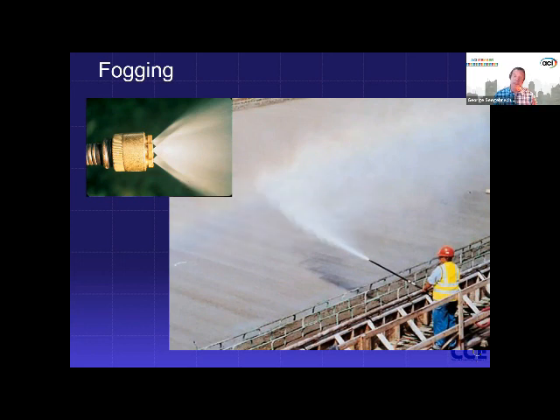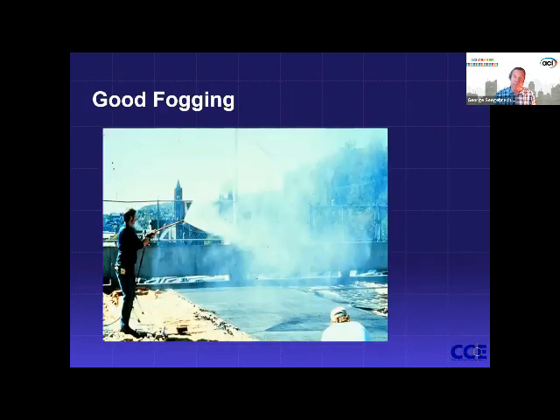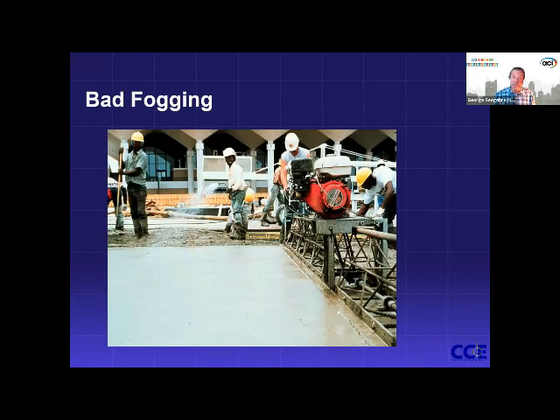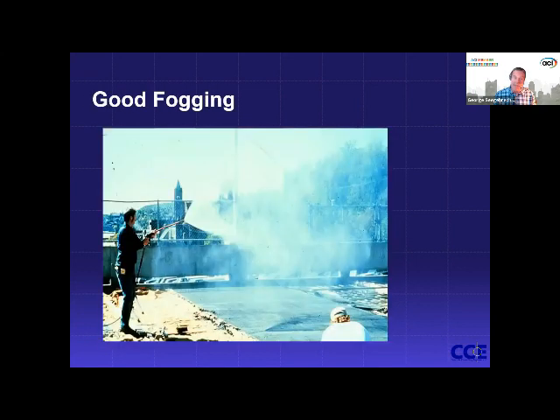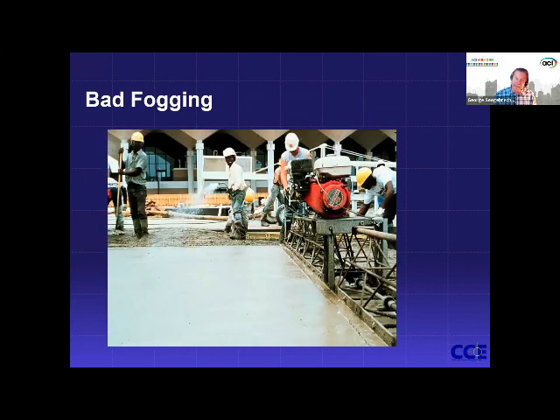Fogging. I'm going to start going through some of these a little faster. Fogging, what you're trying to do is increase the relative humidity over the very surface of the slab, not directing that fog spray, which is an atomized water spray, into the surface, but the 5 feet above to increase the relative humidity there. Another shot. Now this would be bad fogging. The atomizer nozzle is evident here, but it's too heavy of a water spray, and it's going to be damaging the surface.